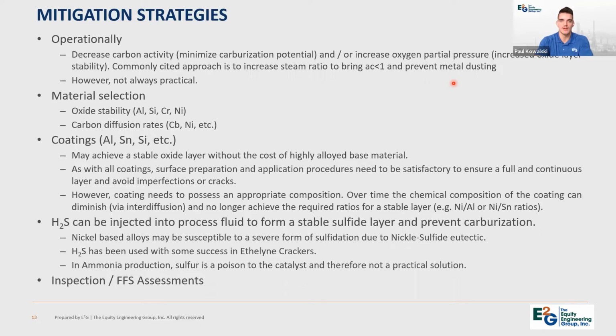So like with many damage mechanisms, operationally is when or how you would ideally like to prevent the damage. If you can change something operationally, then we don't need to worry about the damage mechanism anymore. We don't require material upgrades, etc. However, unfortunately, and especially in relation to the recent operating trends for the desire for increased efficiency, this isn't necessarily practical. Decreasing the carbon activity is not going to occur because we want that higher CO ratio for better efficiency, or increasing the steam to hydrogen ratio. Again, that contradicts the recent operating trends and the desire for greater efficiency, so that also won't occur. So in this case, specifically for ammonia production, this strategy is likely not practical.